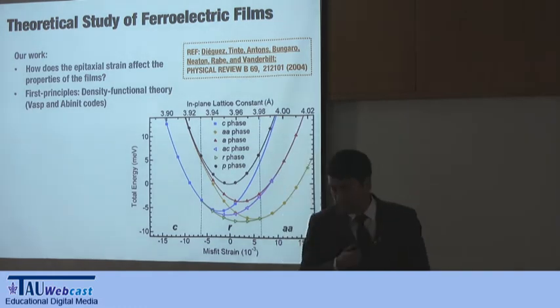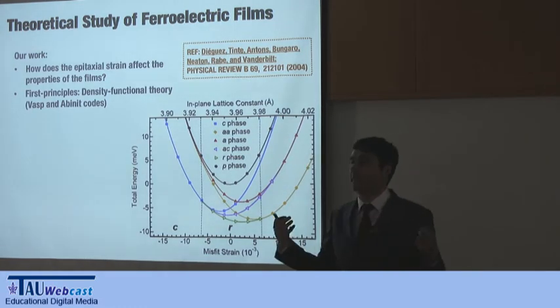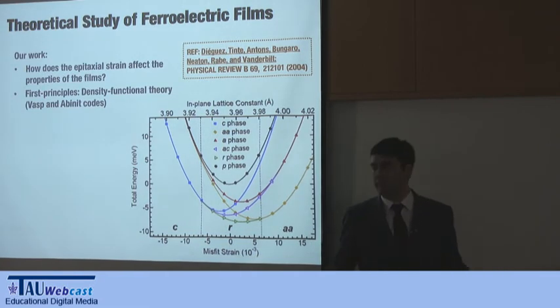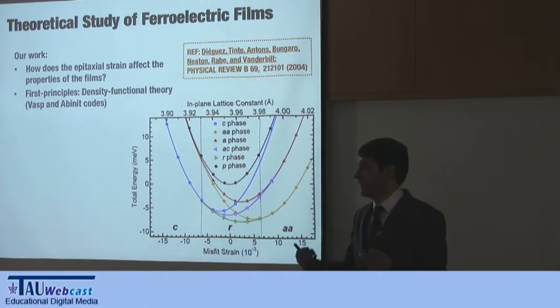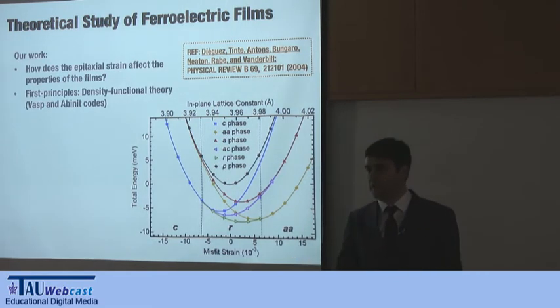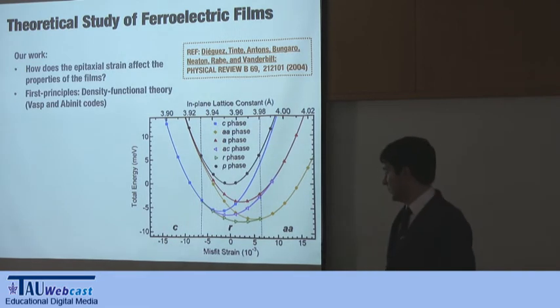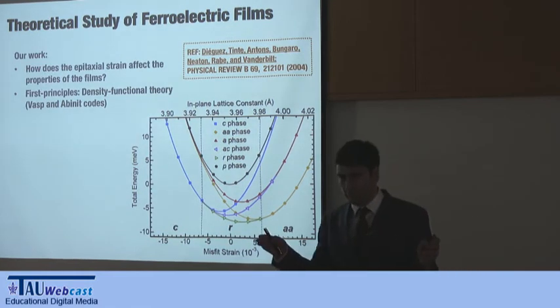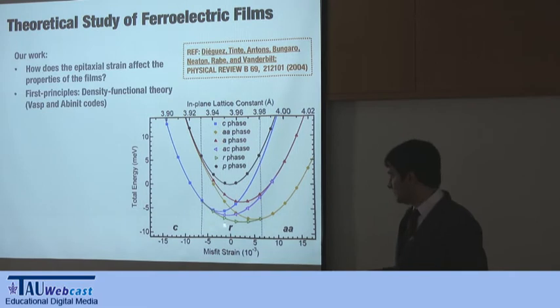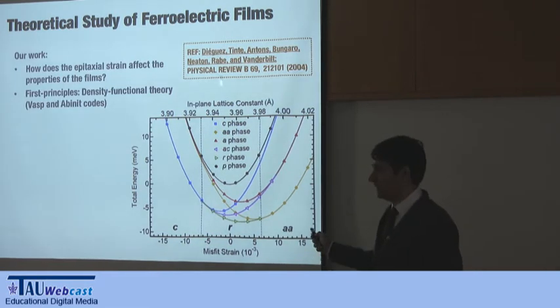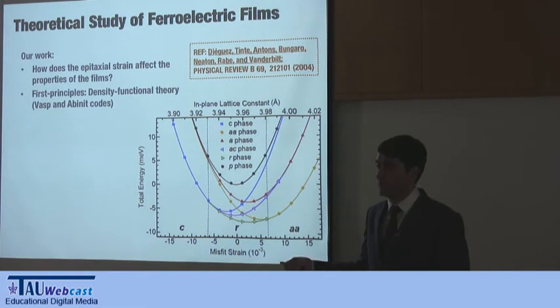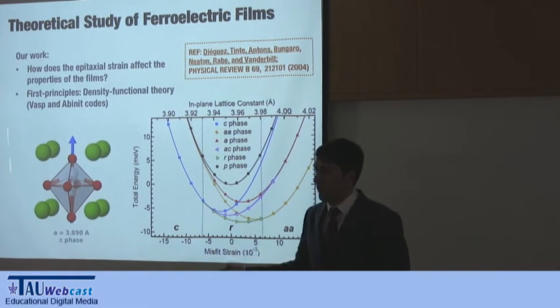So how do we do this? We can map how different the phases that you can have can be, and you can compute the energy for these phases and see which one is the ground state, which phase is the one that the system wants to take. You do this for any misfit strain that you want, so for any distortion of the film that you want. And here they are labeled as they used to be labeled before our study in the literature. It doesn't really matter exactly what each label is. What matters is that each label corresponds to a different direction of the polarization.